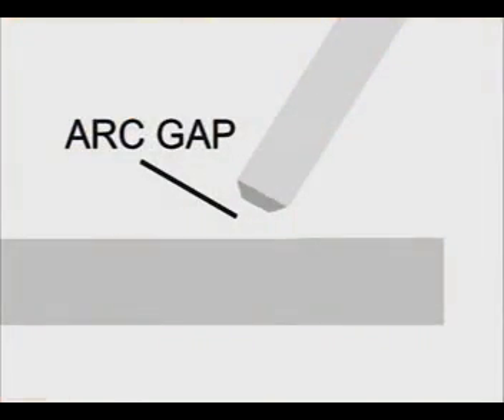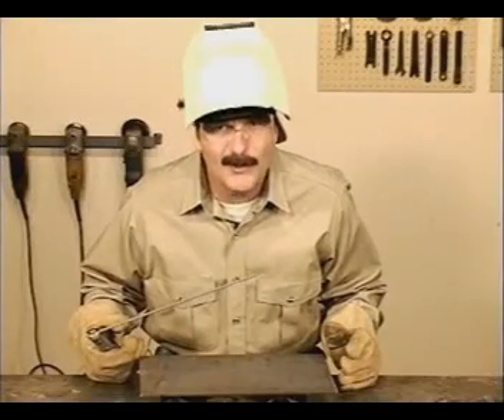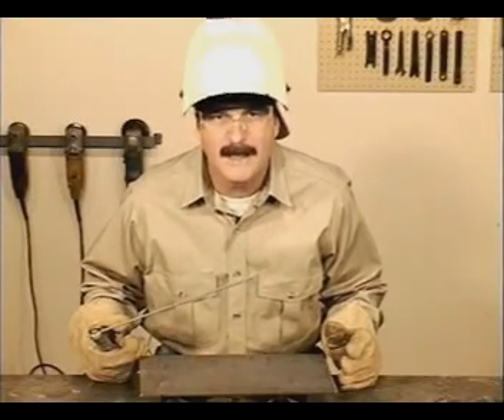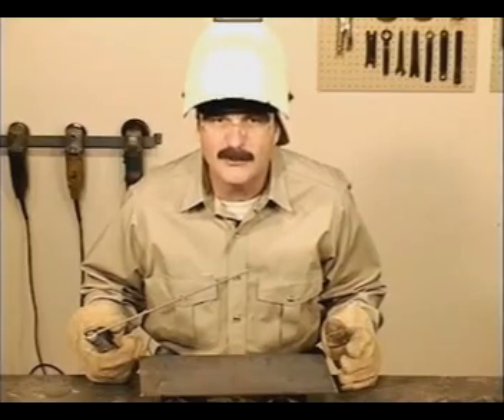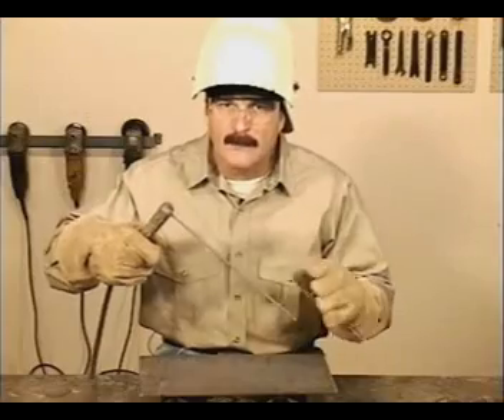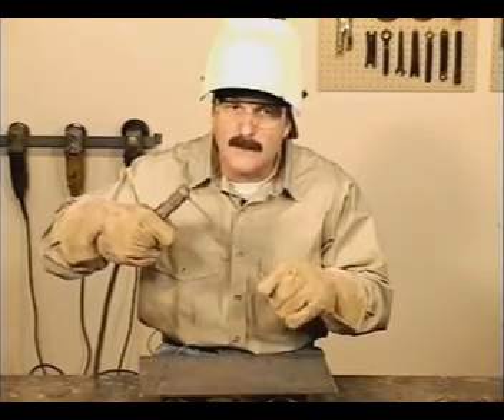During the weld, the tip of the rod is held up off the metal. This is called the arc gap. Having control of this arc gap is one of the first and maybe the most important thing you need to learn. As you're moving along to build weld bead, the rod is being consumed, so you also have to be moving in. And the whole time you need to maintain a constant, uniform gap between the tip of the rod and the base metal.